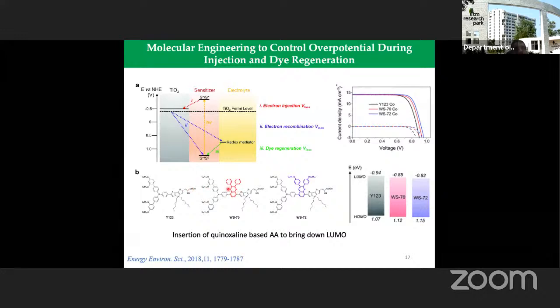He has put in between a quinoxaline moiety, which is an auxiliary acceptor. This nitrogen moiety here will interact with the TiO2 surface by a non-covalent force. Therefore, electron can be injected into TiO2 through this way, or it can be injected through this way. So there are 2 paths by which electron injection is feasible. But when you add more electron acceptors in the structure, the LUMO of the dye gets down, it means it's getting closer to the conduction band of your TiO2. Therefore, the over potential loss can be minimized.